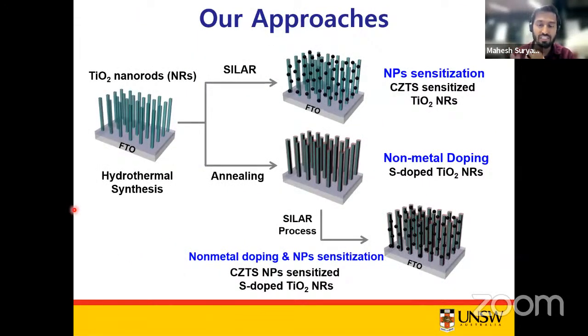This slide shows the different approaches that I have explained in my earlier slides, which we used to further improve the performance of TiO2 nanorods fabricated using the hydrothermal synthesis method. We sensitized them with nanoparticles of copper, zinc, tin, sulfur, called the CZTS compound, which has a band gap around 1.5 electron volt, an ideal band gap to absorb most of the visible light. So we sensitized this CZTS on the TiO2 nanorod arrays. We also doped the non-metal sulfur into the TiO2 lattice to further reduce its band gap, that means to maximize its visible light absorption capability.